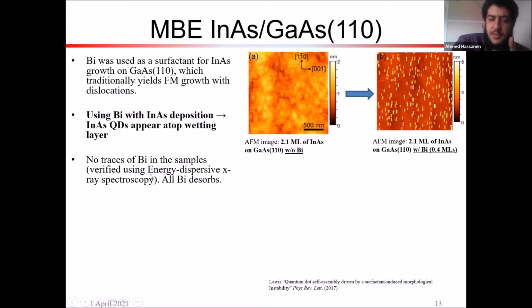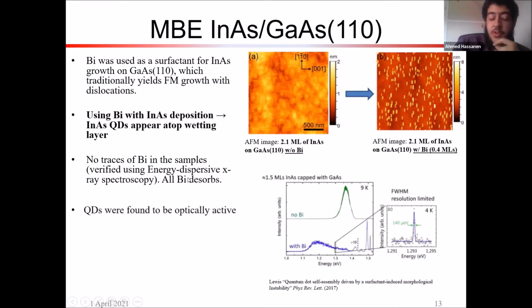And there are no traces of bismuth in the quantum dots. This has been verified by energy dispersive X-ray spectroscopy. So all the bismuth desorbs. And they're also found to be optically active, so you can actually use these as photonic sources.